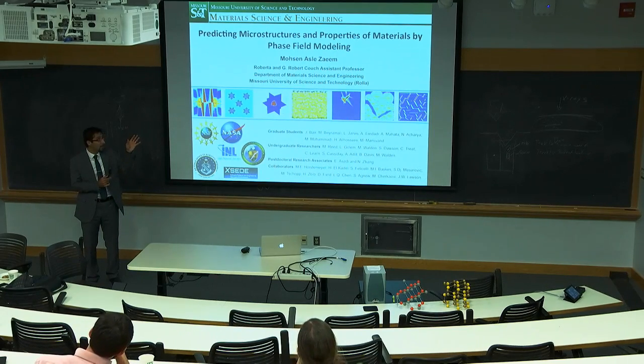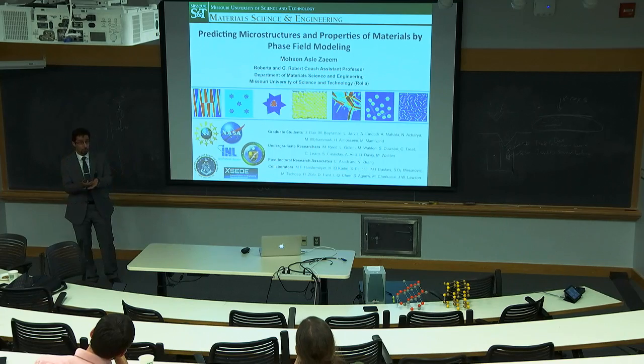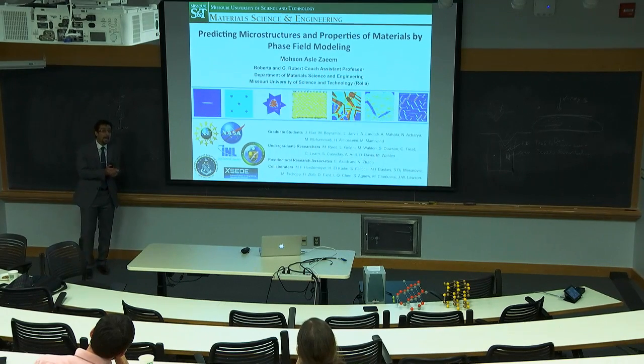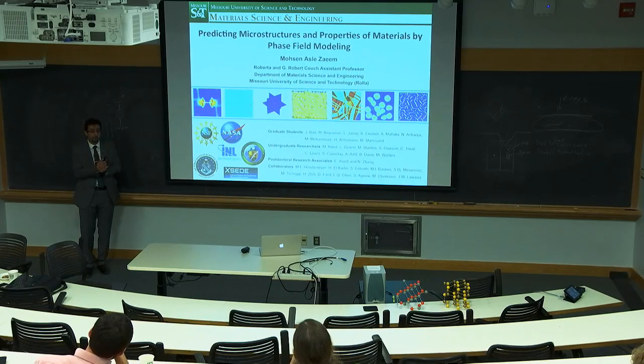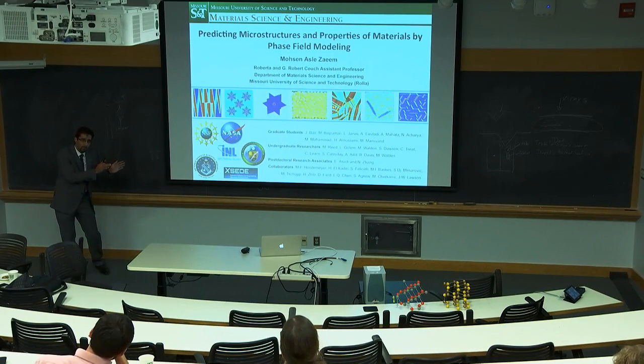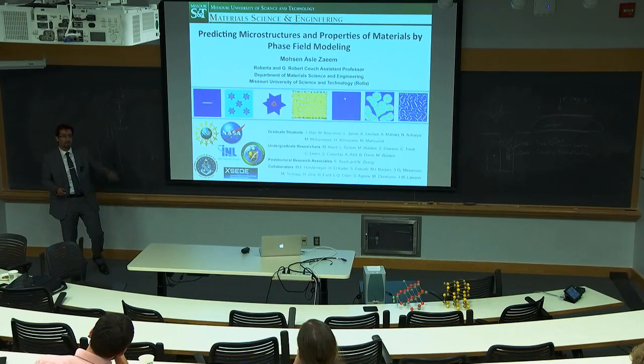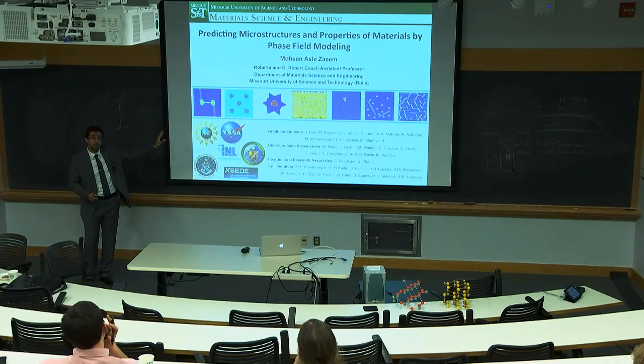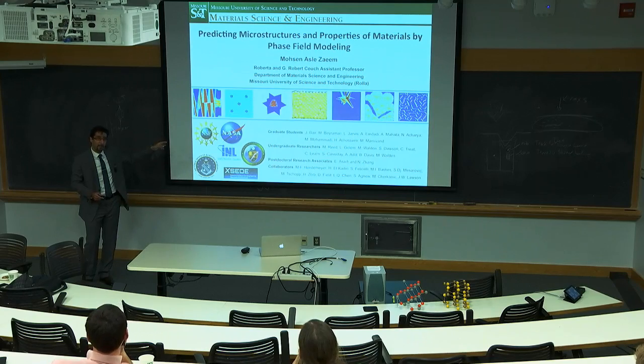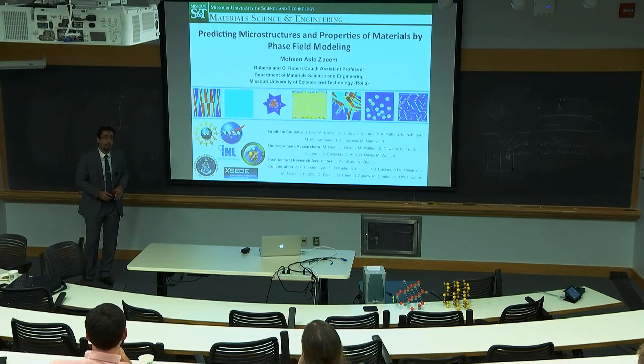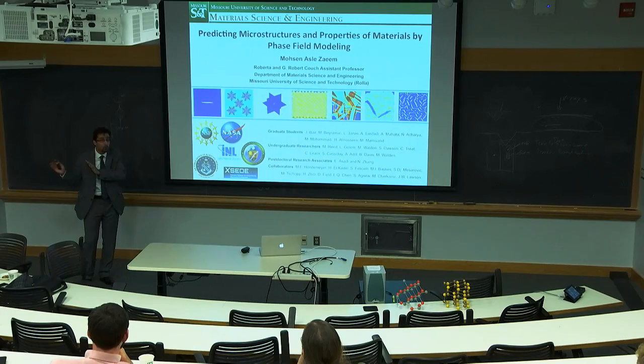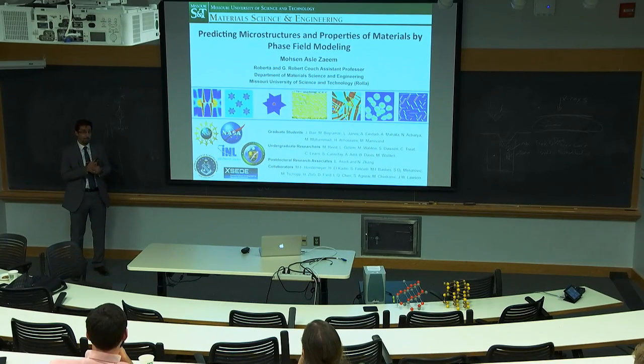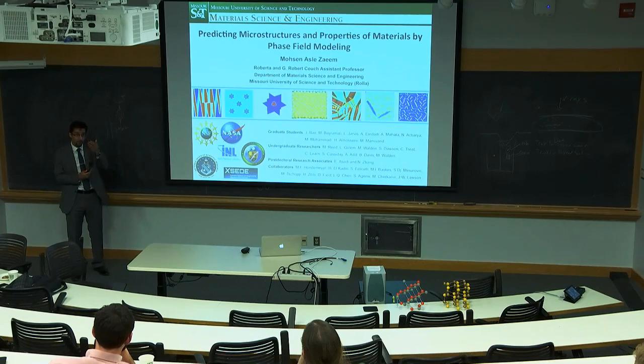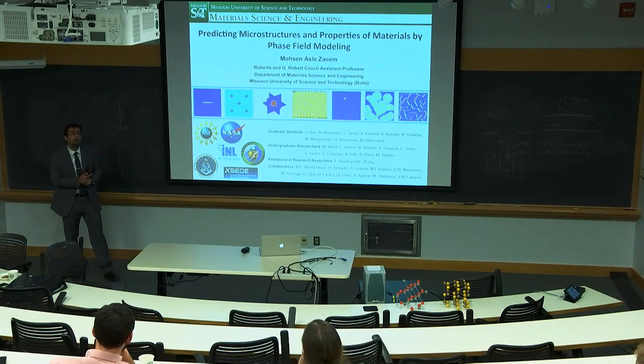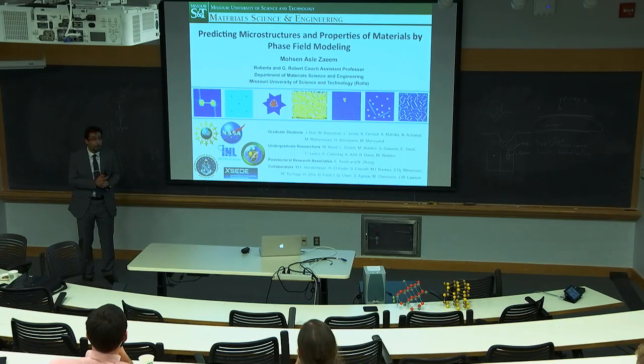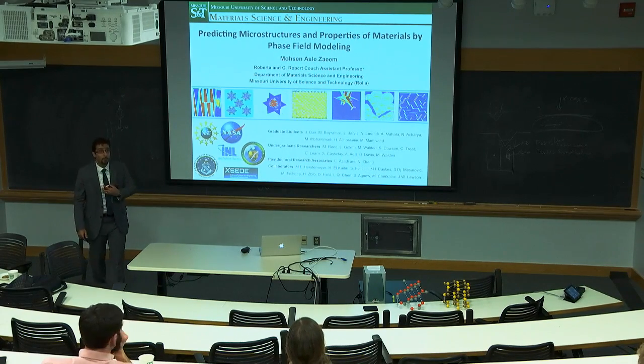But when you go to the actual macrostructure, the question is, can we predict the size and shape of those transformed regions? We need to transfer the data and information from MD simulations to the phase field model. Similar to the model that I showed you for zirconia, there are lots of different things that we transferred from lower scale models, like the transition between dislocation and fully transformed. It's not going to be captured by phase field, but it can be captured by molecular dynamics simulations. That's what raised the question when I was looking at your simulation on zirconia.